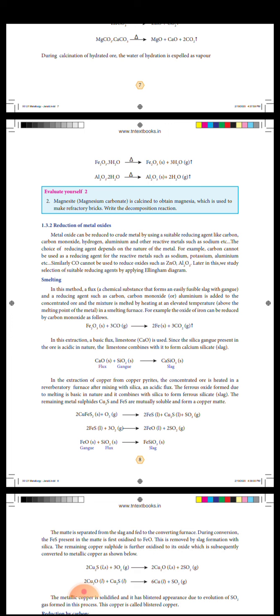In the extraction of copper from copper pyrites, the concentrated ore is heated in a reverberatory furnace after mixing with silica, an acidic flux. The ferrous oxide formed due to melting is basic in nature, and it combines with silica to form ferrous silicate as slag. The remaining metal sulfides Cu2S and FeS are mutually soluble and form a copper matte.